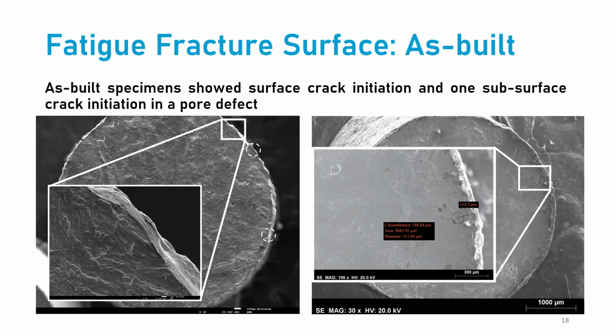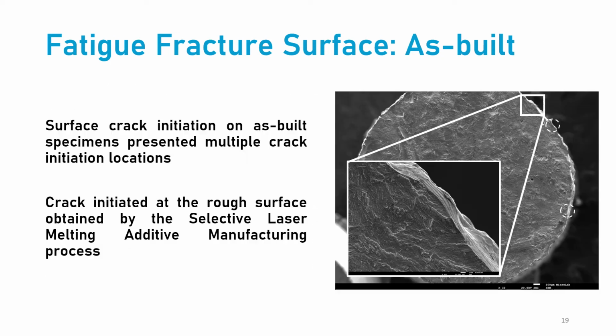Now, taking a deeper analysis of the fatigue fracture surface, first the as-built, we have in as-built predominantly surface crack initiation and only a single subsurface crack initiation in a pore defect. Looking first at the surface crack initiation of as-built specimens, they presented multi-crack initiation locations. For example, here 3 different points were identified, and they all initiated from the rough surface obtained by the selective laser melting additive manufacturing process.